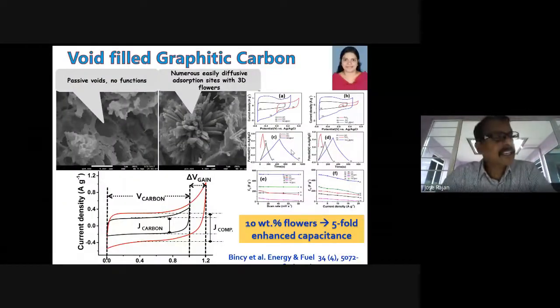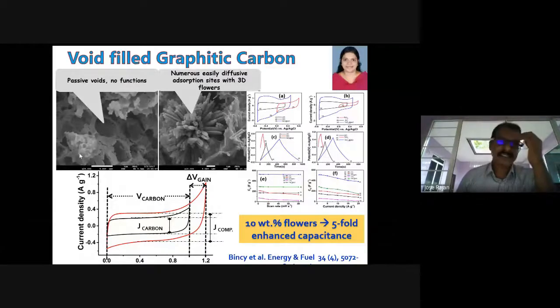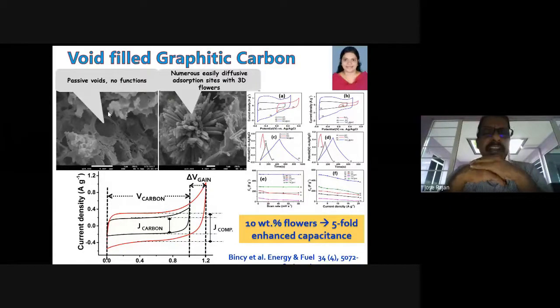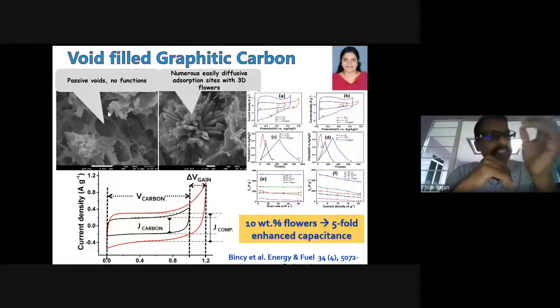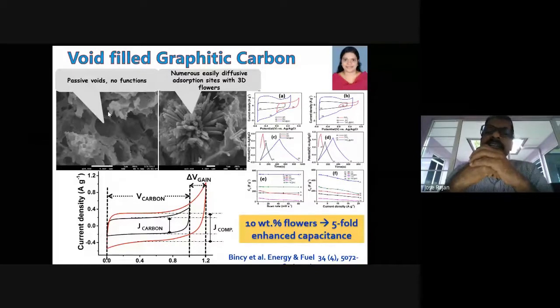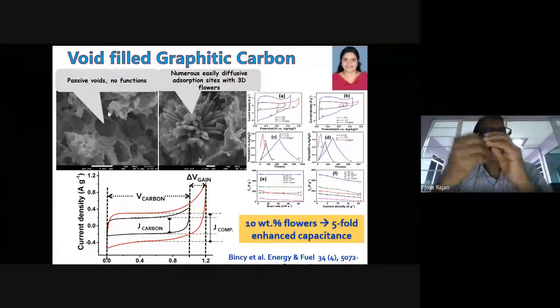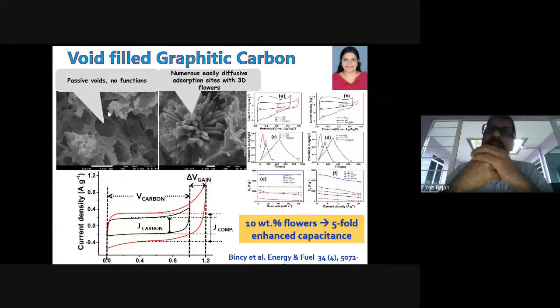And we further noticed that even if we have a carbon performing similar or a bit better than the commercial one, it contains a large amount of passive voids, and these do not add any functionality to the charge storage of this carbon. There, we have developed 10% metal oxide nanoflowers.